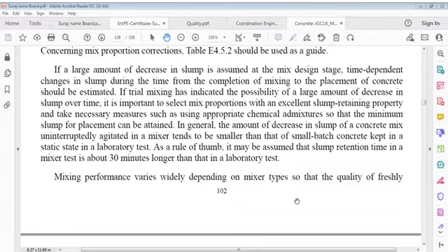If a large amount of decrease in slump is assumed at the mix design stage, the time-dependent change in slump during the time from completion of mixing to placement of concrete should be estimated. If trial mixing has indicated a possibility of a large amount of decrease in slump over time, it is important to select mixed proportions with excellent slump retaining property and take necessary measures, such as using appropriate chemical admixtures, so that the minimum slump for placement can be attained. In general, the amount of decrease in slump of concrete uninterruptedly agitated in a mixer tends to be smaller than that of small batch concrete kept in a static state in the laboratory. As a rule, it may be assumed that slump retention time in a mixer test is about 30 minutes longer than that in a laboratory test.